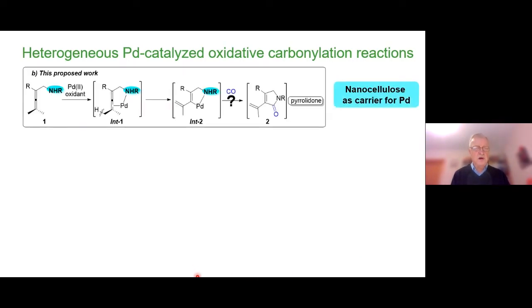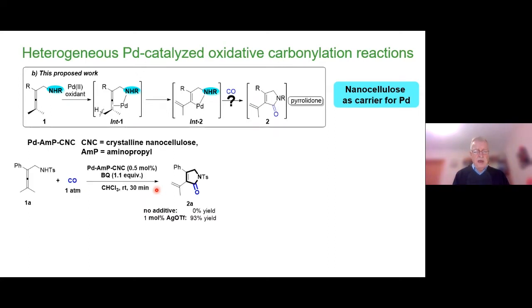So here we are using a heterogeneous palladium catalyst, and the idea was to start with these allenes, aminoallenes, and activate this allene exactly as I discussed on the first slide, where we had palladium now activated to form this dienyl. And now the question is, can we introduce CO here and make these pyrrolidones, this kind of lactams? And CNC is crystalline nanocellulose, so we have this as carrier now for palladium. And indeed, this reaction was tested.